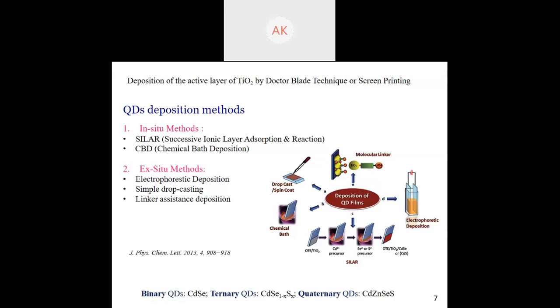You have a Cd2+ precursor solution. You may take cadmium nitrate or cadmium acetate, and you have a sulfide precursor solution, Na2S maybe. So what you do is you have the TiO2 film that is coated on FTO. You dip it in the cadmium solution, you take it out, you rinse the excess out of it, and then you dip it in the sulfide solution. So you have Cd2+ ions which adhere to the TiO2, and then when you dip it inside the sulfide, you form the CdS. So this is what I mean by in situ growing.